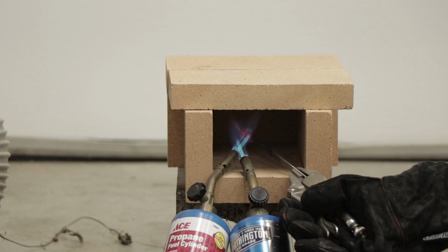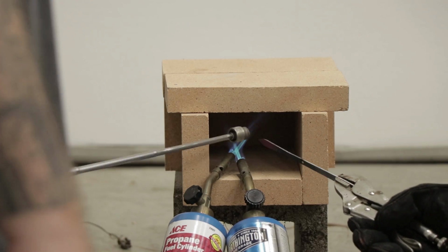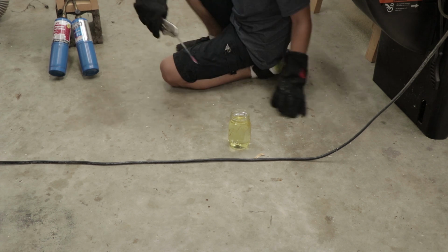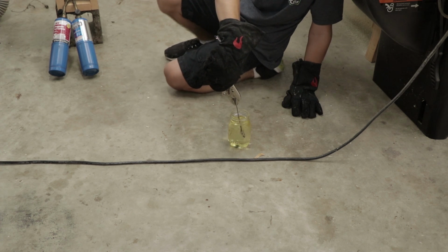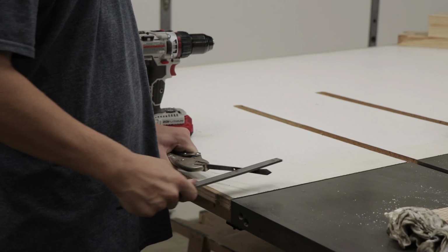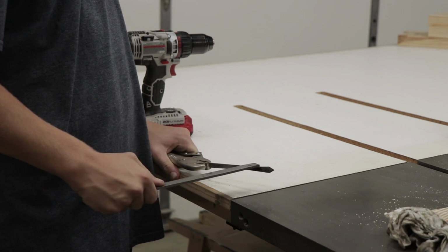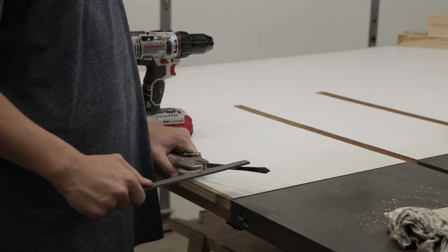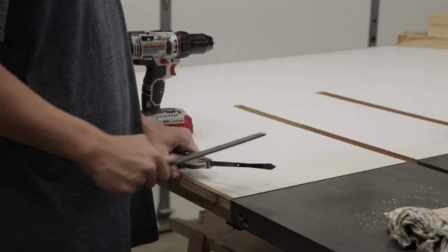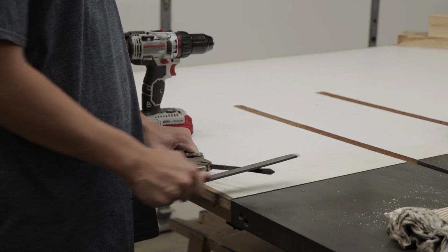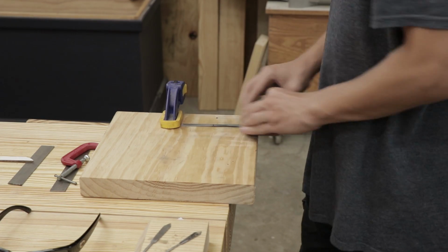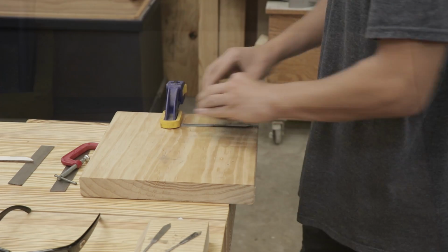Then after a few minutes of heating up in our little forge, we were able to check it to make sure it was demagnetized and then quench it in some peanut oil. After we were done quenching, we were able to check the hardness of the steel by trying to run a file over top of it. The file wouldn't cut the steel and it kind of bounced right over it or skipped over top of it, so we knew we were in good shape.